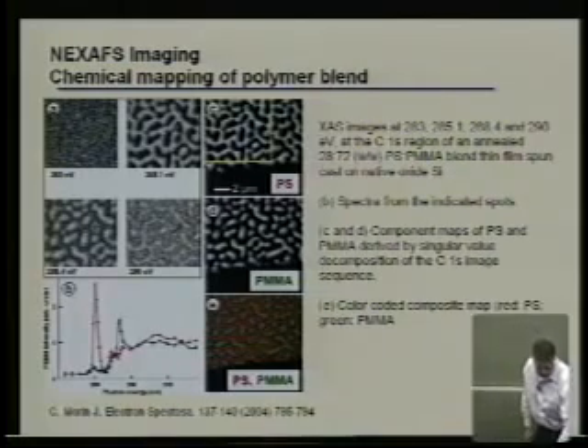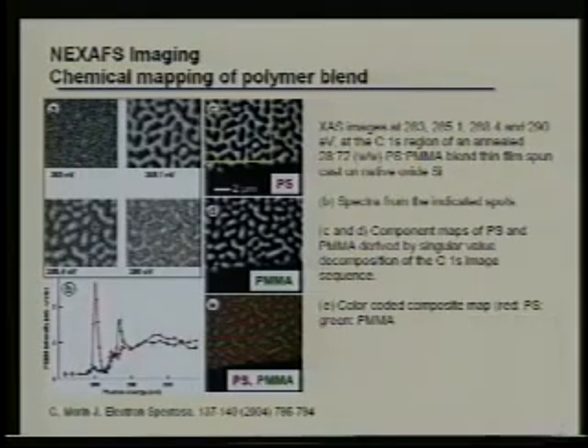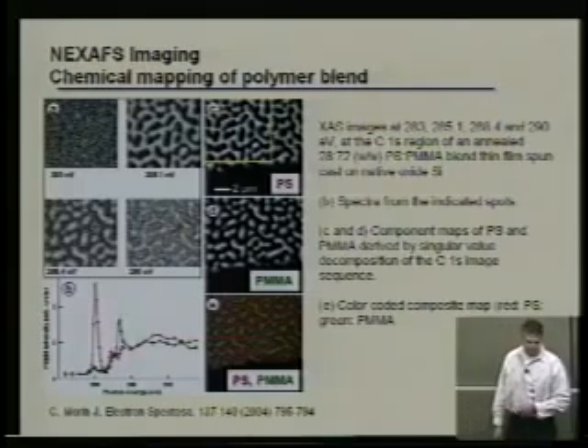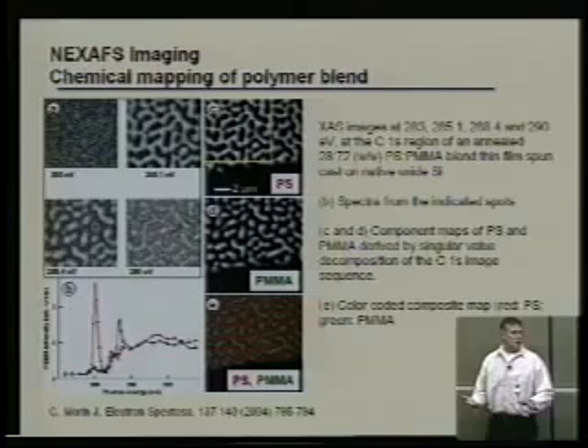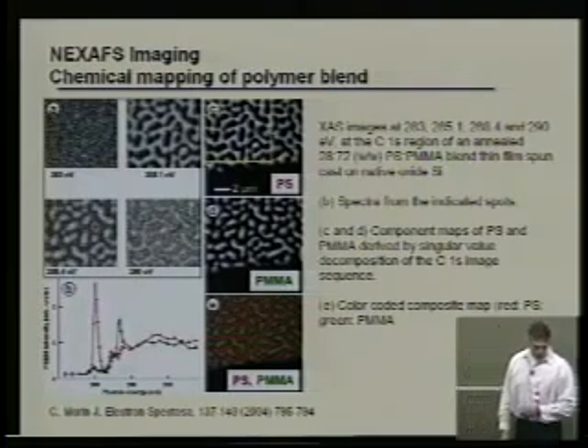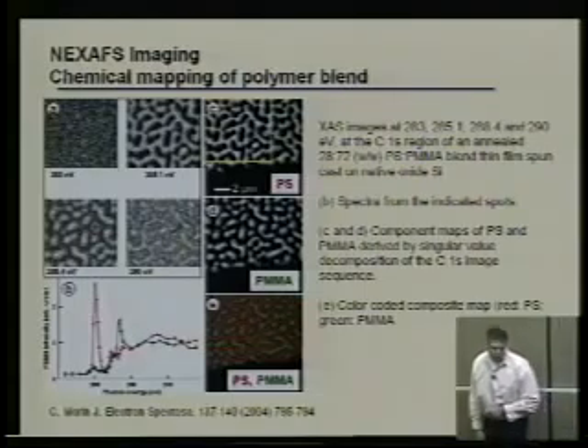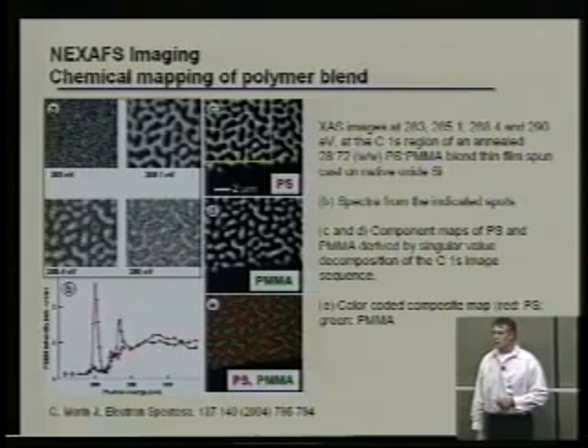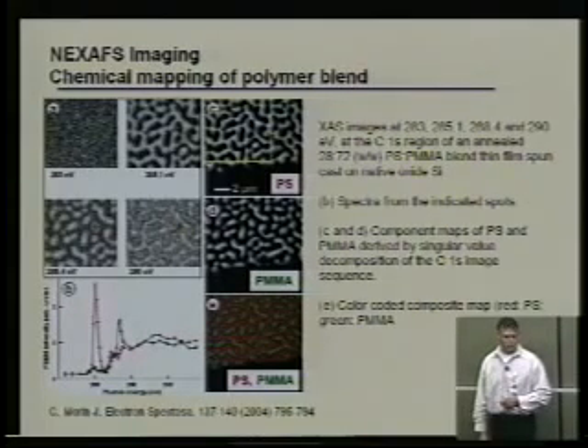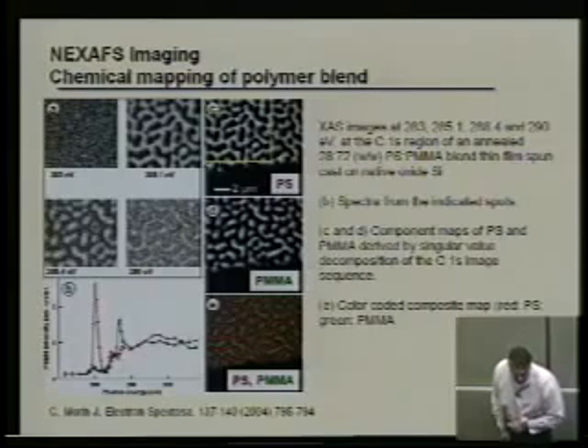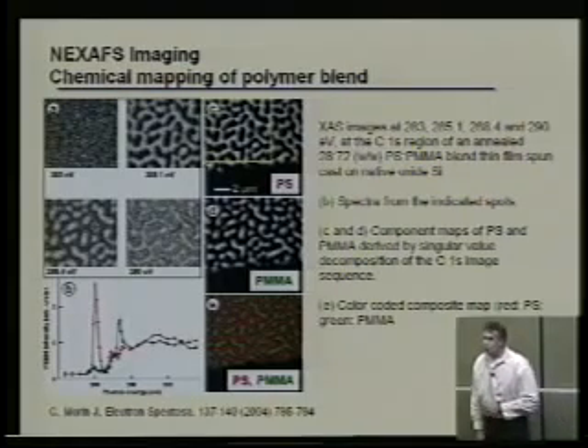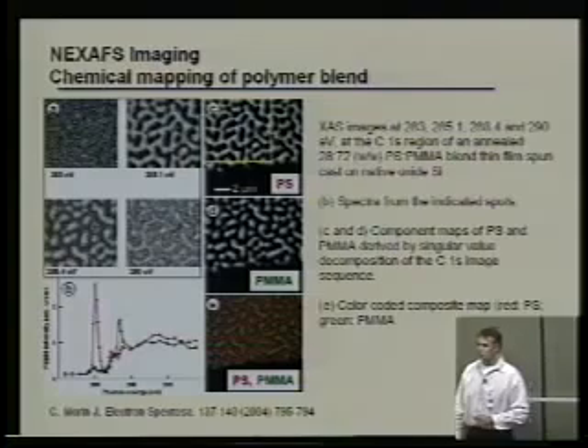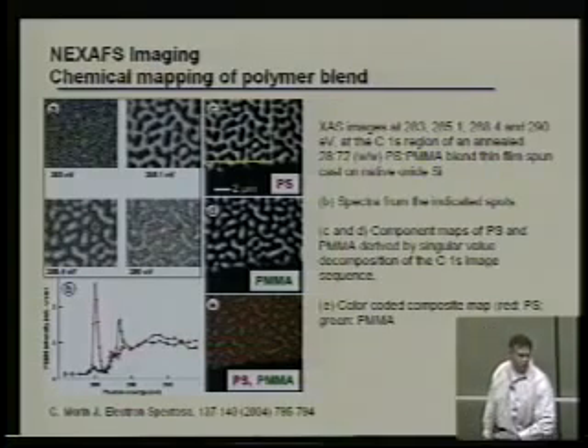So we've got the red plot on the bottom, absorption, is the polystyrene, and the green plot is the polymethyl methacrylate. And we can see that when we excite at 283, we get basically a homogeneous sample, because in that regime, the two absorption edges look the same. And then if we go up to 285.1, that's a large red peak, you can see that you get immediate contrast between the two types of polymers. And then if you excite up at 288, where you're actually on the green line, you can see that the contrast is reversed. And then as you climb up, you start losing contrast.